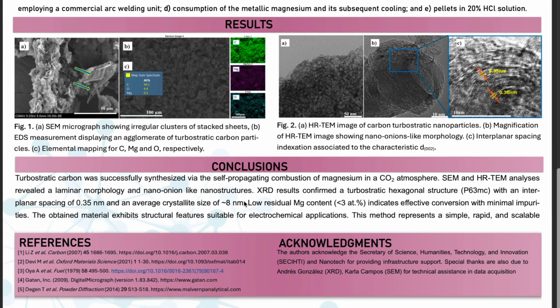In conclusion, turbostratic carbon was successfully synthesized via the self-propagating combustion of magnesium in a CO2 atmosphere. SEM and HRTEM analyses confirmed a laminar morphology with nano-onion structures and an interplanar spacing of 0.35 nanometers. This technique offers a simple, rapid, and scalable route to produce high-quality carbon materials tailored for energy storage and electrochemical applications.